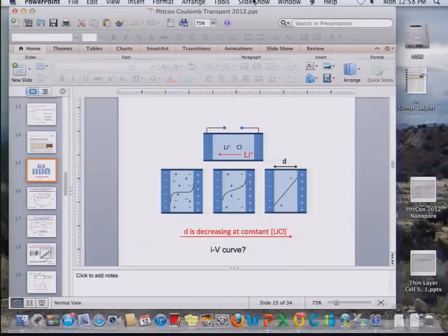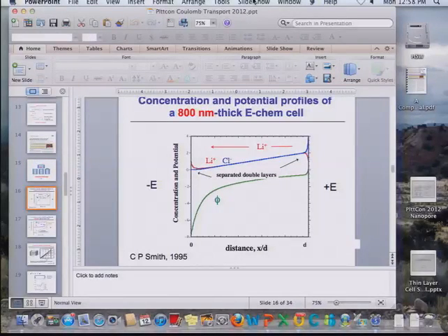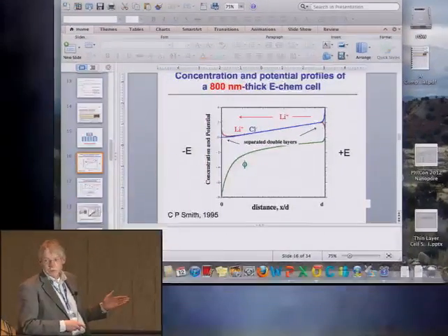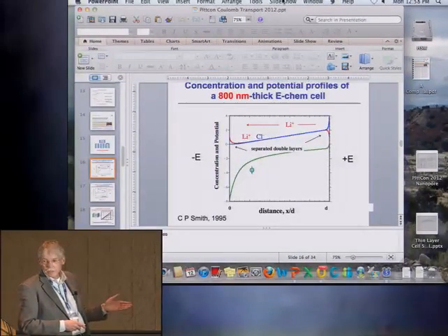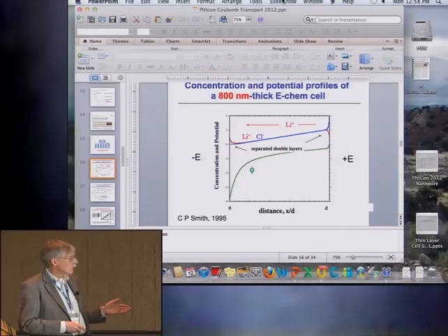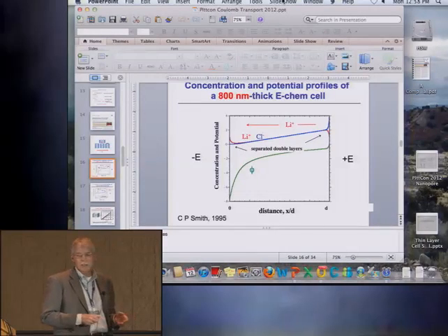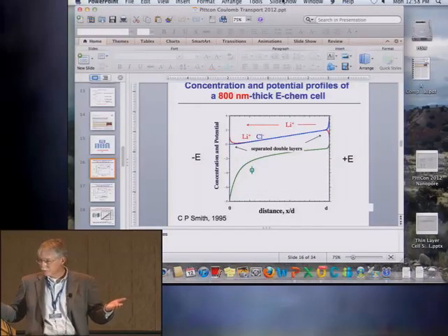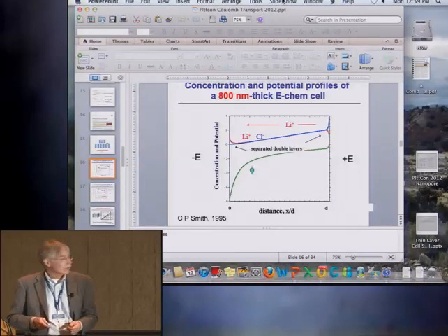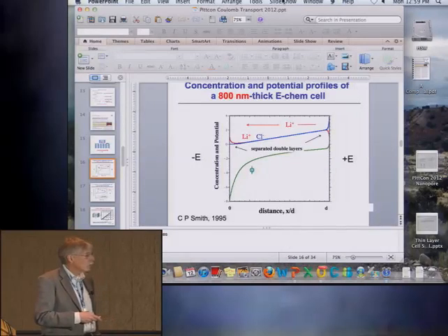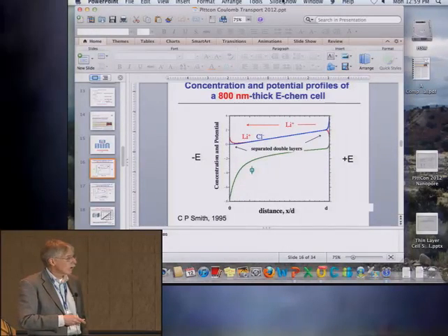Okay, so what happens when you decrease the thickness of the cell in terms of the current flow? I'm going to show you current-voltage curves, but first, this is for lithium coming out of the right electrode, positively charged, transported across the cell, and then disappearing over here. Here's the cathode, and here's the electrical potential profile. This is for a very thick cell, 800 nanometers in width. These are the concentration profiles. You pretty much have electroneutrality all through the cell except at the edges where you expect the double layers to exist. And there's a concentration gradient. The lithium is being driven primarily by diffusion from the right over to the left.